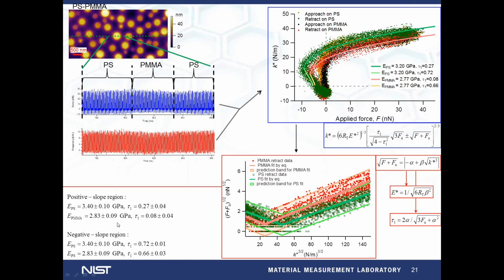So the numbers are here. Polystyrene was used as a reference material with 3.4 gigapascal. PMMA comes out at 2.8 gigapascal. The transition parameters are 0.3 for polystyrene, which compares well with the 0.5 that we got before in force volume measurements. For the PMMA, the transition parameter is 0.1, close to the DMT limit.